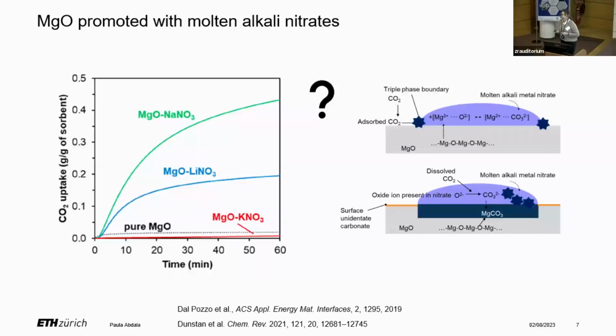Well, this has been a question for several years in literature, and people have different hypotheses on how this material works. So some researchers say that magnesium and oxygen, so magnesium oxide, is dissolved into the melt, and it migrates to the triple phase boundary, where adsorbed CO2 reacts, and at the triple phase boundary, magnesium carbonate forms. Other researchers say that the surface carbonate of magnesium oxide prevents the CO2 diffusion into the bulk, and the molten salt, what it does is breaking this layer. Other researchers suggest that actually CO2 and magnesium oxide are both dissolved into the melt, and somewhere inside the melt, magnesium carbonate is formed, either like particles or really like a layer moving in depth into the bulk.